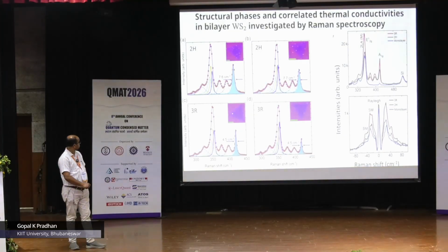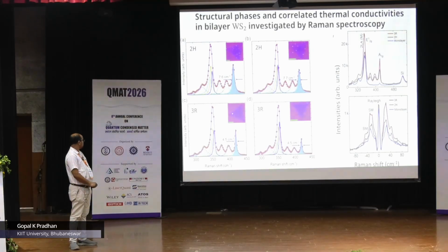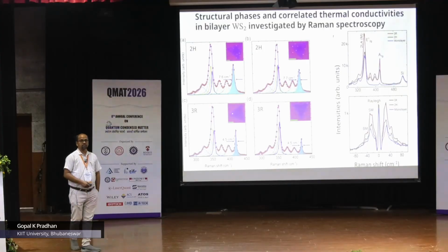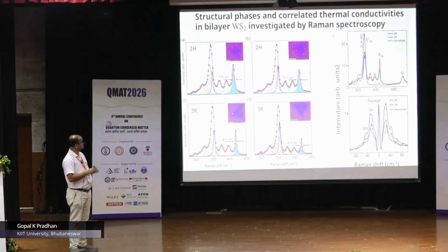One of the markers is the FWHM, or the width of this A1G mode, and you can see for the 3R phase, this is what we found. If the phase is 3R, then the width is much smaller, only 4.5 centimeter inverse, and if it is the 2H phase, it is about 7.5 centimeter inverse. So that is a marker to tell you whether you got a 2H or a 3R phase, right.